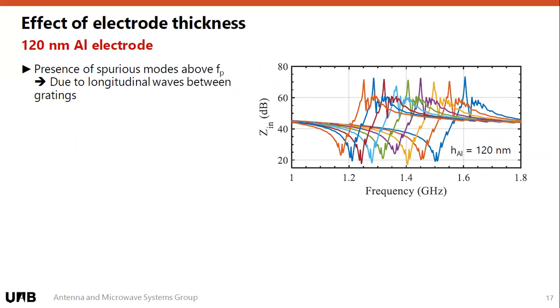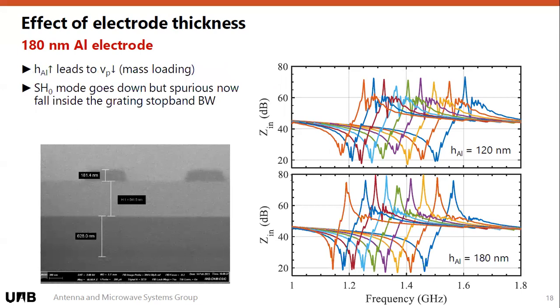These modes, Jordi did some simulations, and they are mainly due to longitudinal waves that actually propagate through the two gratings. So we went for the 180 nanometers electrode, and we saw the following result. When you increase the electrode thickness, you're adding a higher mechanical load on your resonator, so you're moving your phase velocity slightly downwards. But the distance between the gratings and the modes propagating between the gratings do not change from their frequency at which they propagate. And now, since our resonator has moved slightly downwards, the energy that was being trapped inside those longitudinal modes is now inside the stop band bandwidth, or the reflectance bandwidth, of the grating we have.